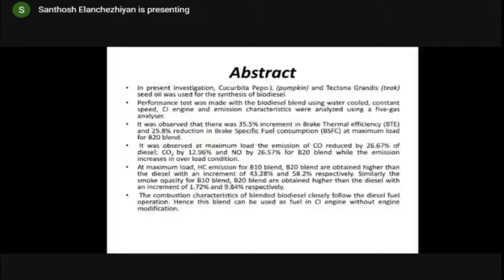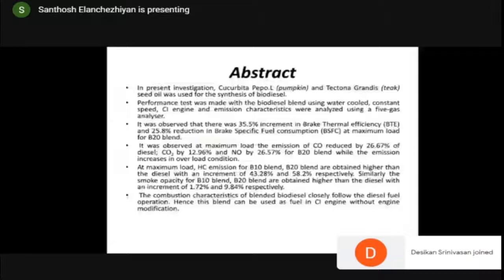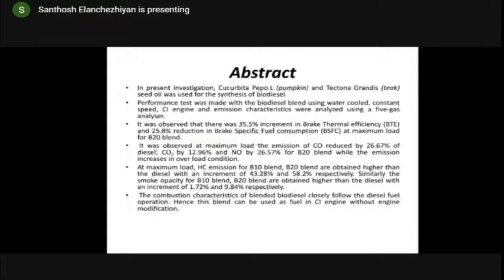It was observed that at the maximum load the emission of CO reduced by 26.67% compared to diesel, CO2 by 12.96% and NO by 26.57% for B20 blend, while the emission increases in the overall condition. At the maximum load, HC emissions for B10 blend and B20 blend are higher than the diesel, with increments of 43.28% and 58.2% respectively.